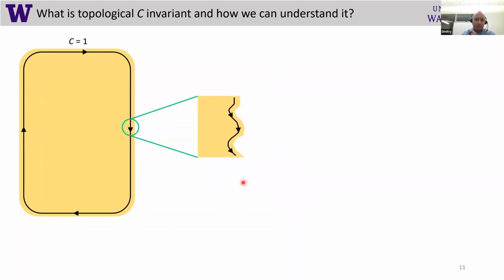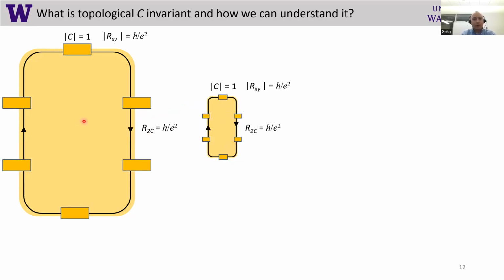And even if we look very closely at this sample on nanometer scale, for example, we can use maybe STM or TEM, we can see that essentially there is some disorder on the edge, even on the atomic level, but this edge state, regardless of this disorder, would continue propagation along this edge. And another aspect of this is that if we change the shape of the sample, change the dimensions of the sample, change the aspect ratio of the sample, we would always get the same Chern number, the same Rxy, and also the same two-terminal resistance between two terminals.